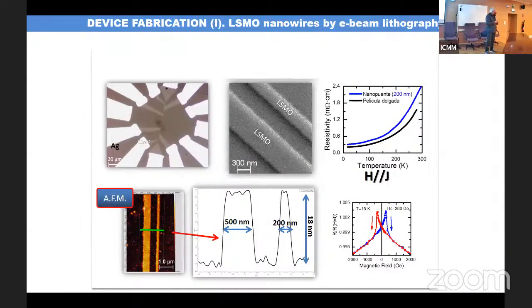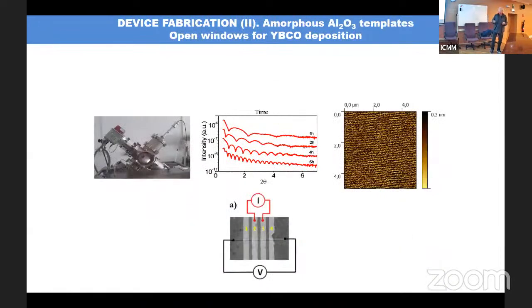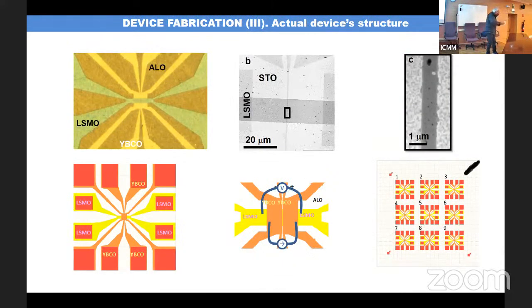As I was telling you, the strategy is ex situ. We first grow a manganite film. We pattern a wire with electron beam lithography, right? And then since there is no resist to be used as a mask, we engineered a mechanical mask with amorphous alumina. We developed a whole process to grow this amorphous alumina and make trenches by electron beam lithography, right? And we deposit the YBCO in these trenches.